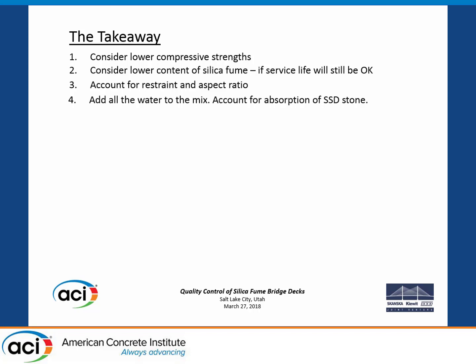You know, the stone will take 1%. The sand will take 1 or 2%, depending on the kind. But you account for that. When you do your moistures in the morning, you burn the sand in a cooker, you cook it dry, and you're measuring dry sand. Well, when you put the water in, some of the water's got to go into the sand. So that's not free water for hydration. So you take that into account. So you put in all the water you can to keep the temperatures low. Use ice. Don't cure it.